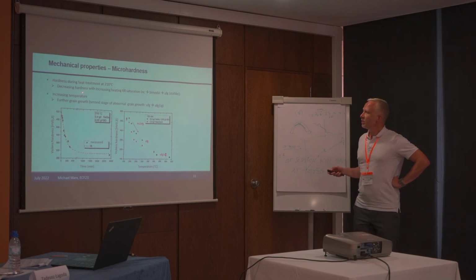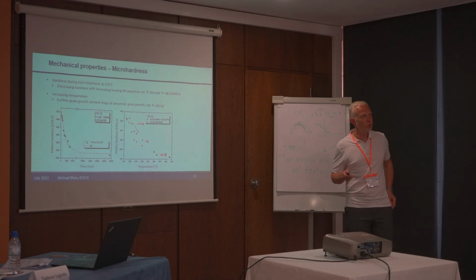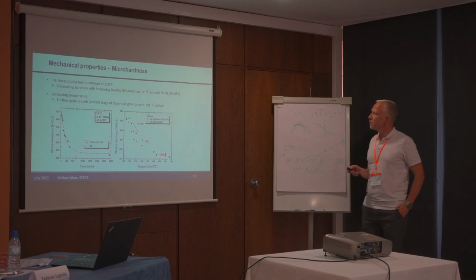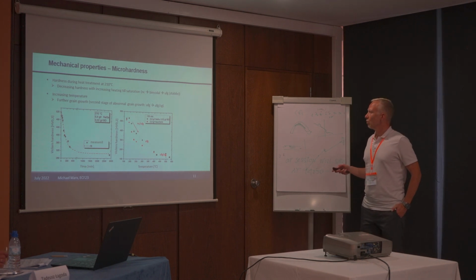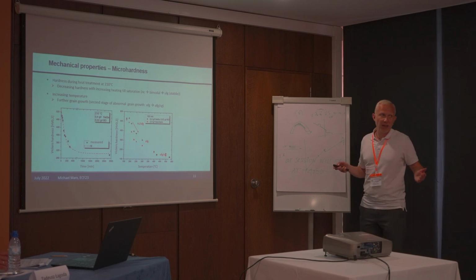The hardness during the heat treatment decreases, as you can see here. This is at 210 degrees C for different time, and this here is for 150 minutes at different temperatures, and in both cases we have grain growth and the hardness decreases with the temperature and with time, as expected.